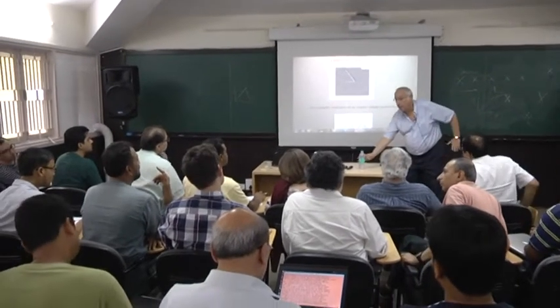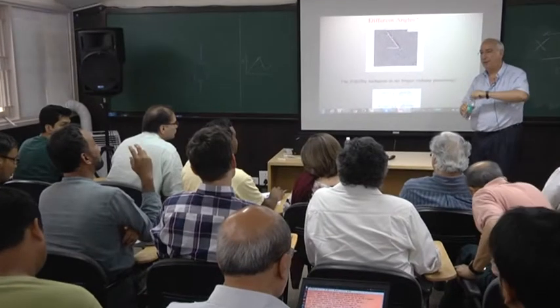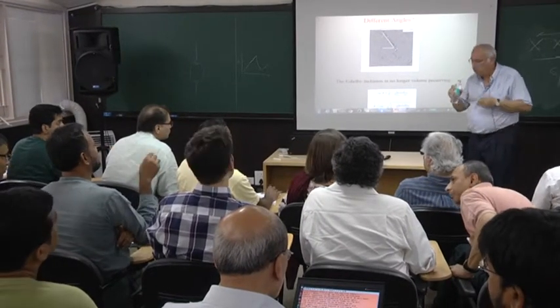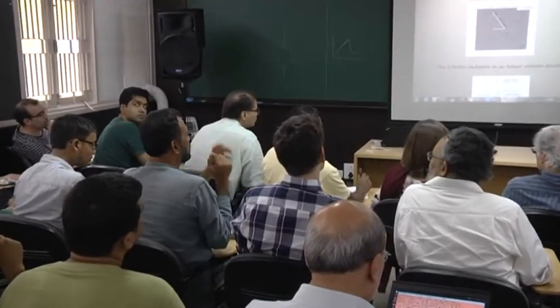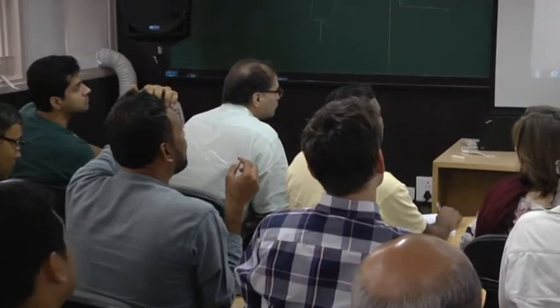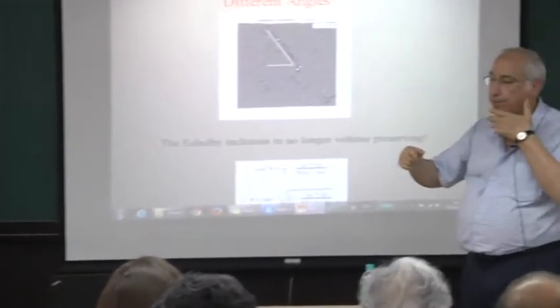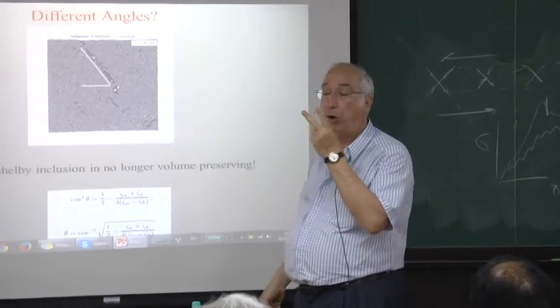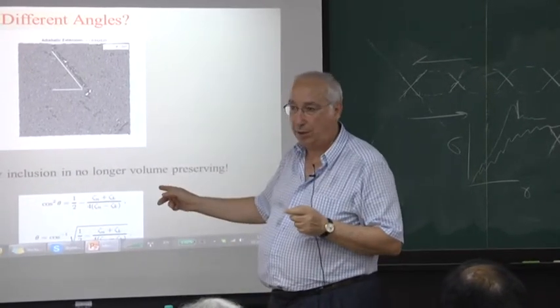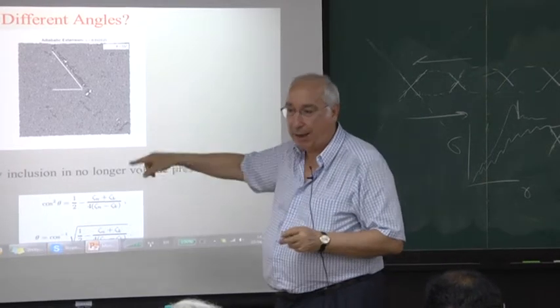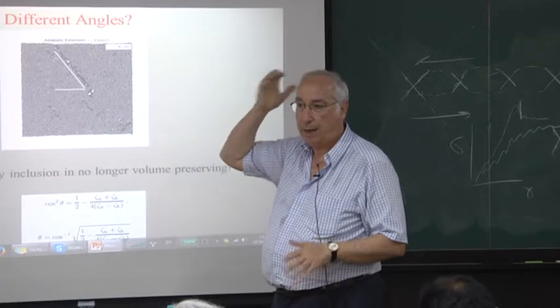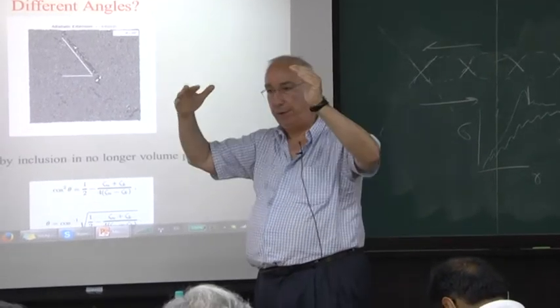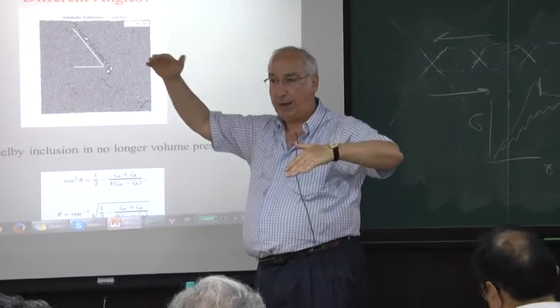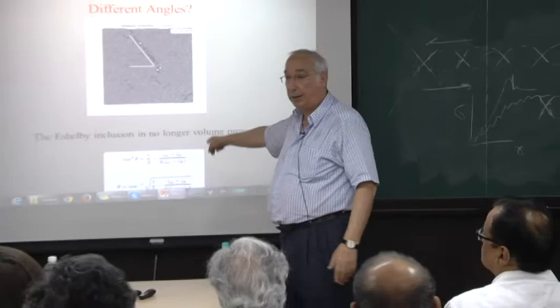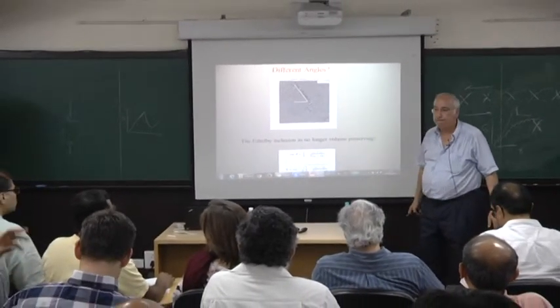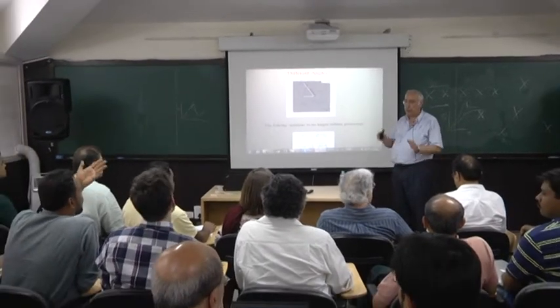It's not a detail, it's very important, yeah. The answer is that when you have uniaxial, the solution for the Eshelby is no longer a function only of epsilon star, which is a combination of those, but it now depends on three parameters: zeta n, zeta k, and the Poisson ratio. And that solution now will look different and will respond differently to the far away external strain in choosing a different angle. But this is an analytic calculation of that minimum. Of the Eshelby solution, yeah, exactly.